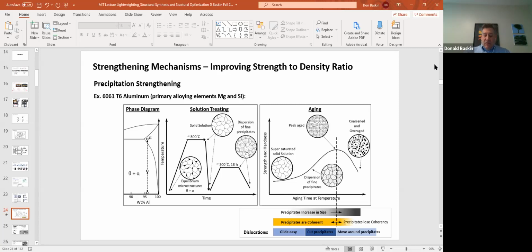I have been involved with situations where a supplier was tasked with making an aluminum part for my company, and they said they bought a billet of 6061. They machined this part out. It worked fine. The dimensions were great. And then they decided for some reason to heat it up. They heat the material up and these precipitates grow. And then when they're done heating up, you have a material that has only 65% of the strength it's supposed to. And then you get a mechanical failure.